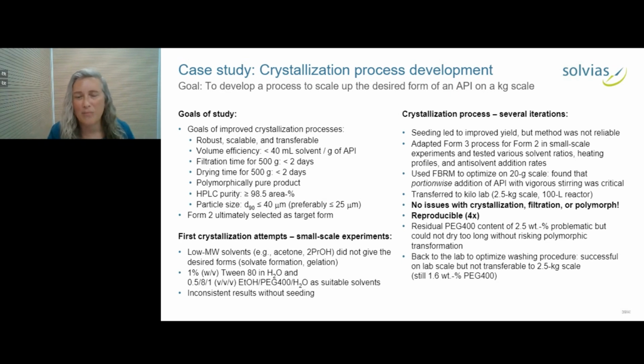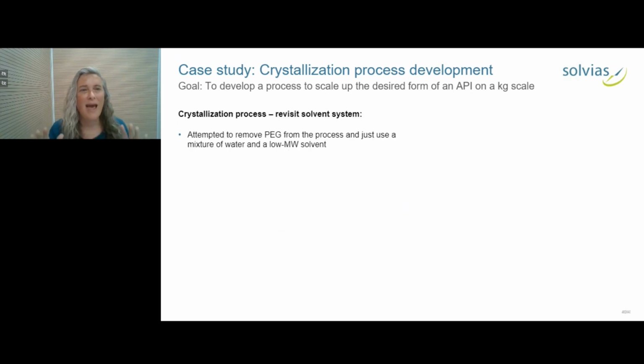We came up with a procedure that was successful on the lab scale, but was not as successful on the 2.5 kilogram scale. There was still 1.6 weight percent of PEG 400, a bit better than 2.5, but not good enough. At this point, we took a step back and said, okay, are we really stuck with using PEG? Is there not another solvent that we could use?